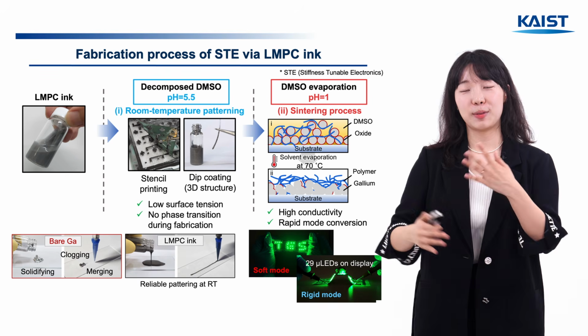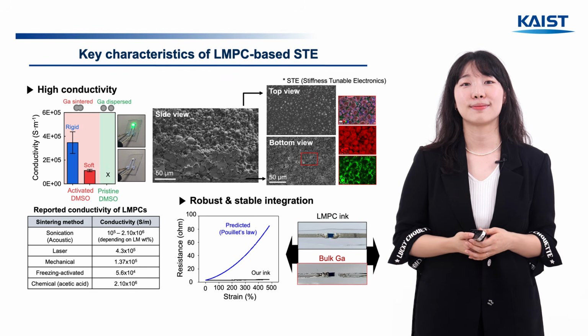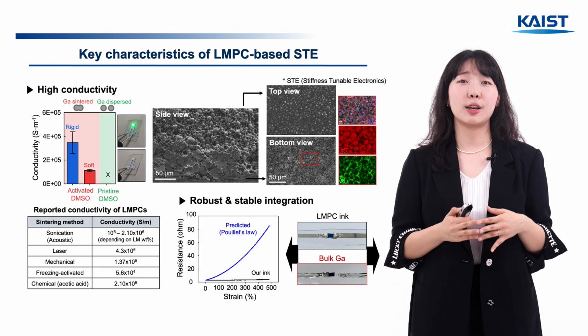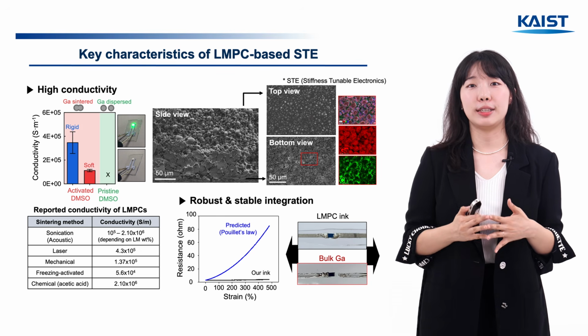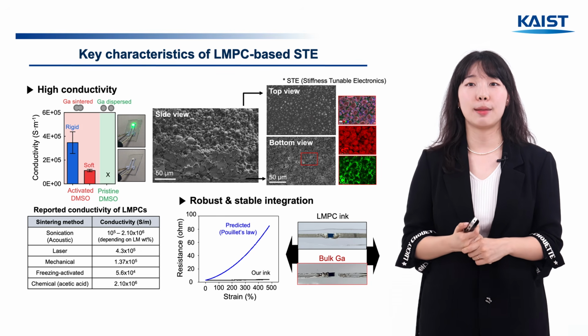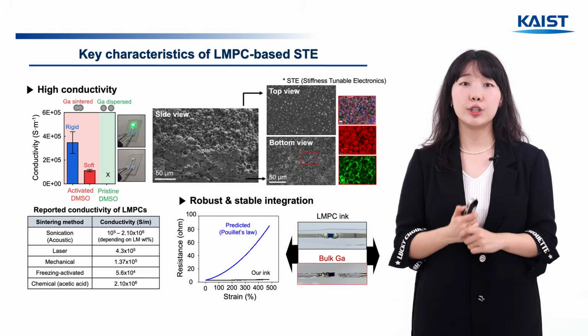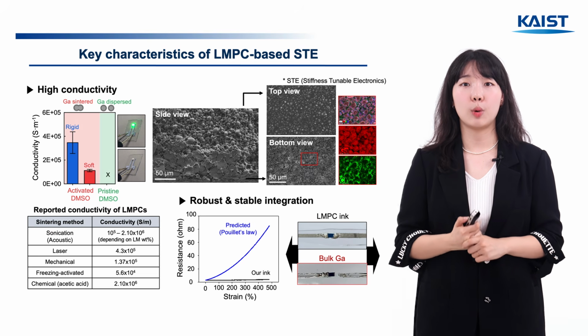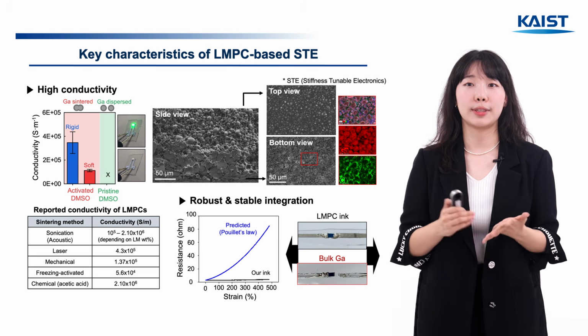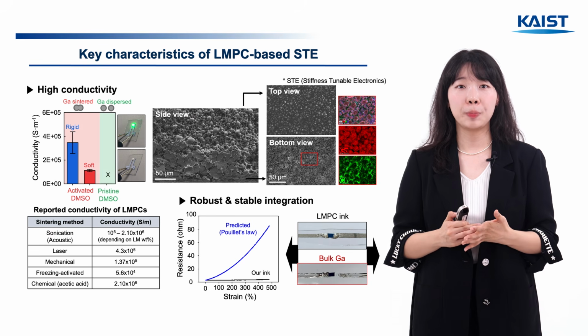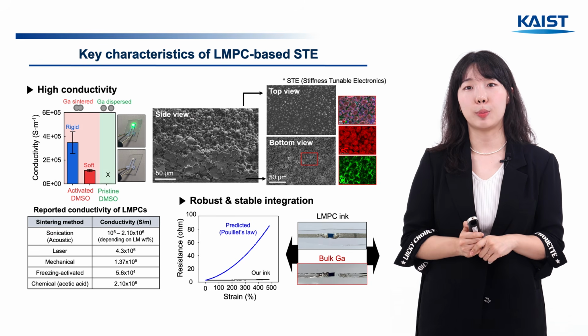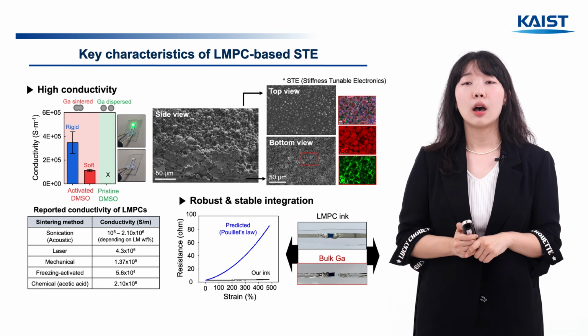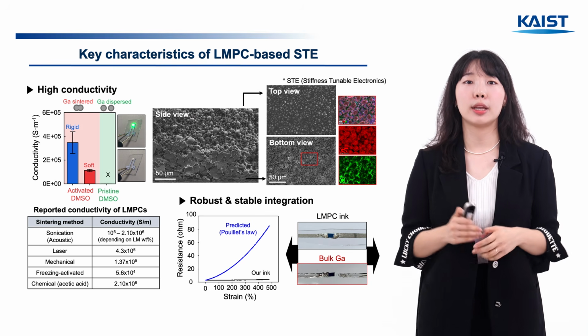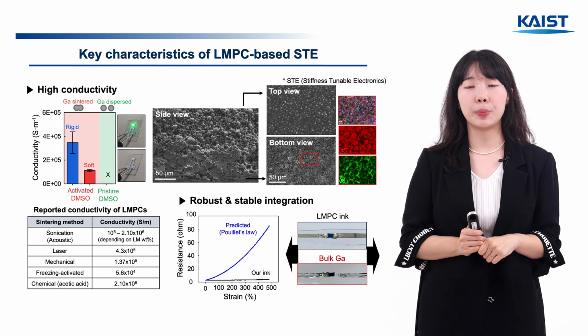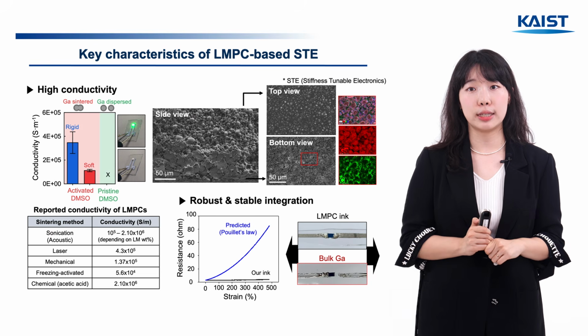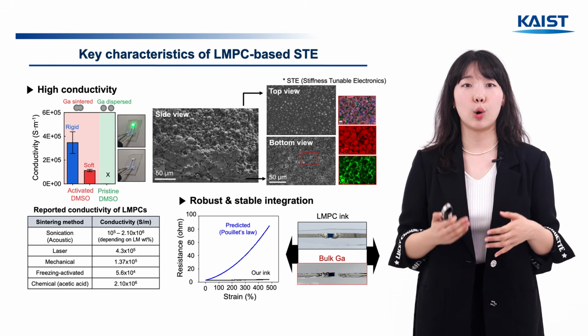We analyzed the conductivity of the device using 4-wire Kelvin resistance measurement. Rigid mode was higher, but both modes were on the order of 10 to the 5th Siemens per meter, and this is comparable to other reported LMPC inks. Also, even under strain, because the material is particle form, it showed a much smaller resistance change than the Pouillet's law would predict.